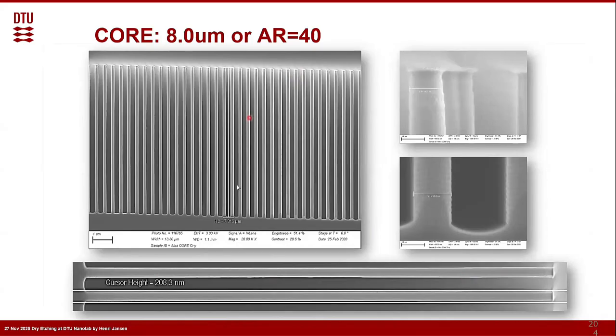Here we turn it 90 degrees, and you can see the line, how nicely it follows the extremely sharp ion angle distribution function. So we really go to low pressure during the bottom removal step to make sure that the ions are only removing at the bottom, and that they don't hit anything from the sidewall. That means we need a very sharp distribution. We could do that because it's a very short time that we need it, so the selectivity can still be very high.